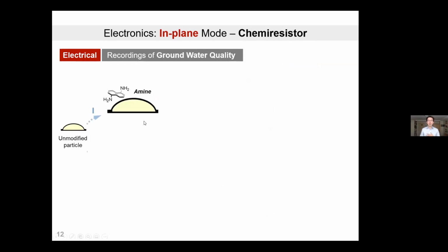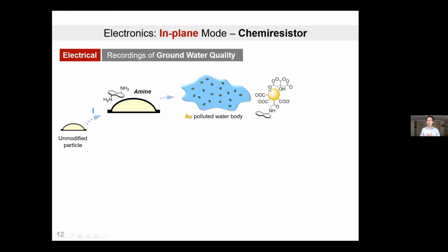So here, with the same graphene particle, we can selectively adhere onto the surface an amine functional group, which will grab onto the gold nanoparticle inside groundwater. So this becomes a heavy metal nanoparticle sensor within groundwater. By dispersing the particle into the groundwater and then harvesting them back afterwards, you can measure the conductivity change of its surface, and this is very selective and sensitive.